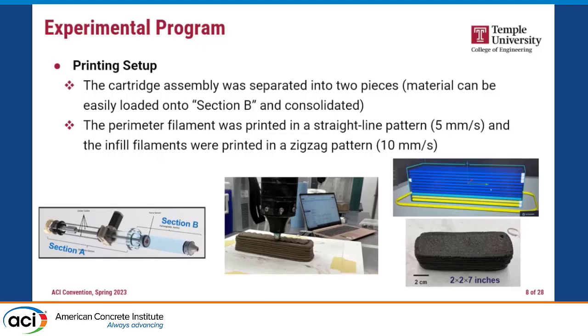Regarding the pattern of printing, we use this: the outer or perimeter layers are more straight lines, and the infill is more zigzag. The main reason is that we got better dimensional stability from this pattern. After printing, we cure the samples. The OPC system is cured for 28 days inside water or calcium hydroxide solution. For the alkali activated system, we adopted 2 different types of curing. The first method, we seal cure them for 28 days. The other method, we heat cure them at 60 C for 7 days.